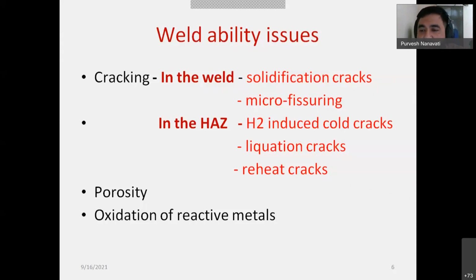So these get diffused, and during solidifying of the weld metal, this hydrogen cannot get a chance to escape out of the solidifying weld pool. As a result, it traps there, and such hydrogen in a susceptible microstructure like martensite develops cracks, right? Because they occupy more space on becoming molecular hydrogen.